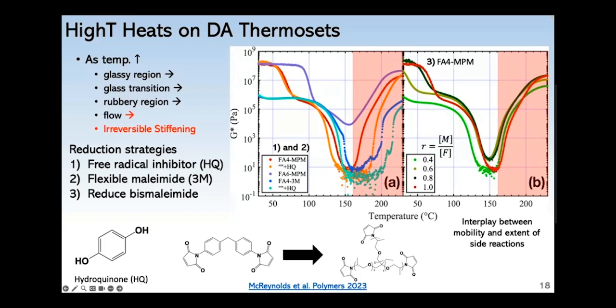For a final and third strategy, we just tried to reduce the maleimide content in order to reduce the self-reaction. So to go through these, the red curve is the 1-to-1 stoichiometric case. The dark green is 0.8, medium green 0.6, and lime green 0.4. And I think to our surprise a little bit, changing the maleimide content doesn't really significantly reduce the impact from the side reaction, which we partially attributed to this dynamic interplay between mobility from using less crosslinker and from how far the side reaction could go because of that increased mobility.